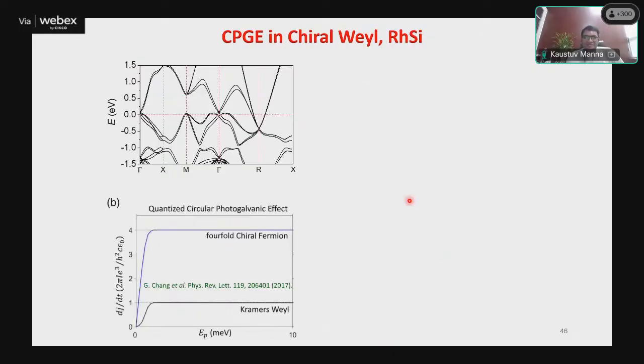Now we take the rhodium silicide compound. As you can see, this is the gamma point and this is the R point. Therefore, until this much incident energy, whatever valence band to conduction band excitation would happen is not allowed, because the conduction band is already filled until this much energy. So until this much incident energy, whatever quantized DC current you observe is basically unfiltered DC current from the gamma point. That is what we expected.